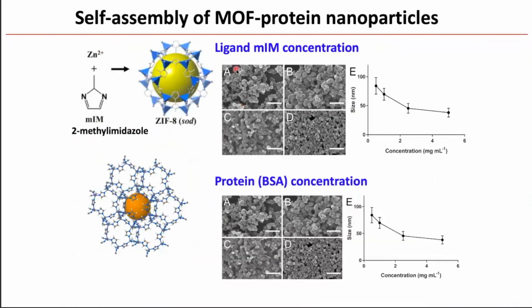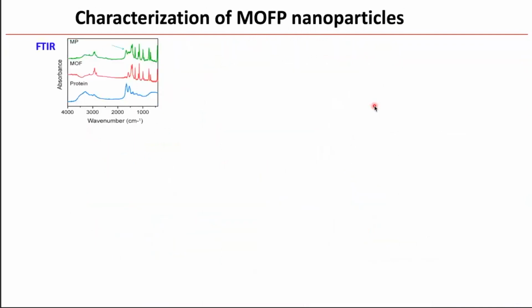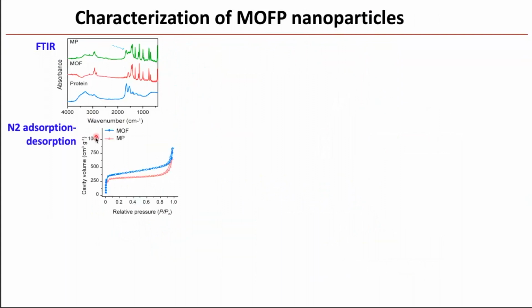So this slide shows some basic characterization and optimization of the MOF-protein nanoparticles. You can see we can change the organic ligand concentration and also the protein concentration to control the size of the particles. In general, we are using a particle size from 50 to 100 nanometers. And then we further characterize these MOF-protein nanoparticles using infrared spectrum. And we also use nitrogen adsorption-desorption to confirm this is a porous nanoparticle.